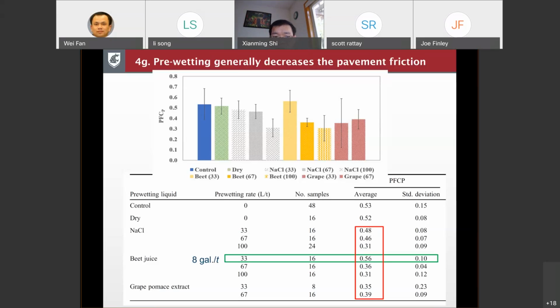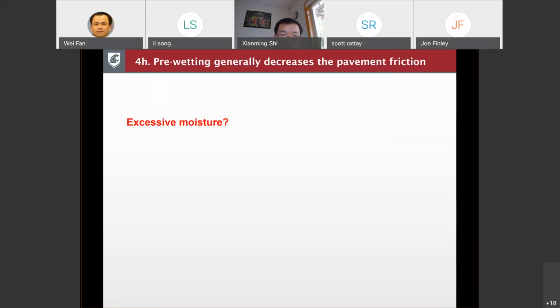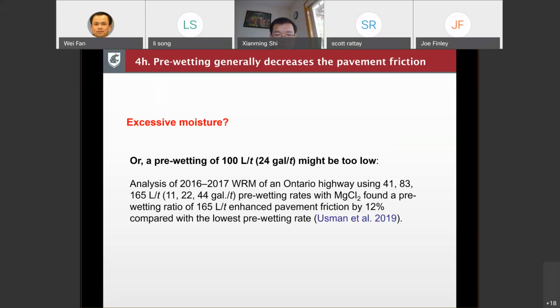So what's going on here? We actually want the higher friction coefficient. Usually, just to give you an idea, any number lower than 0.3 or 0.4 would be slippery pavement. So one possibility is the excessive moisture we introduce. Keep in mind when we are putting especially a high pre-wet rate, we're introducing a lot of water into this mix. The other possibility is the application rate.